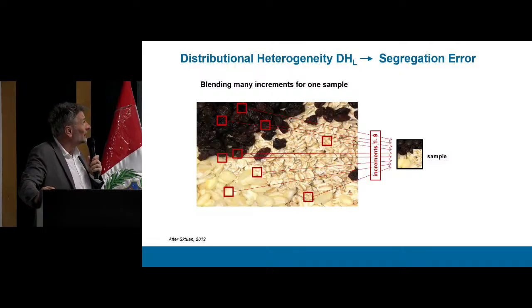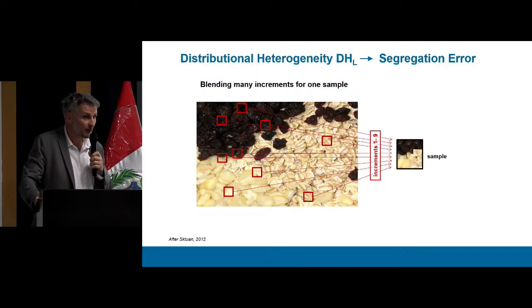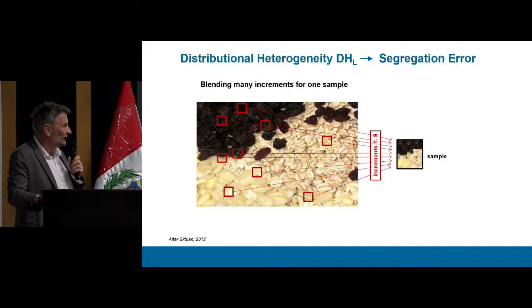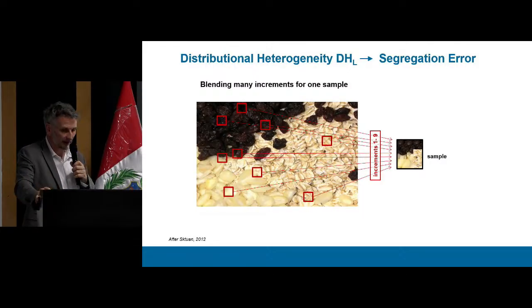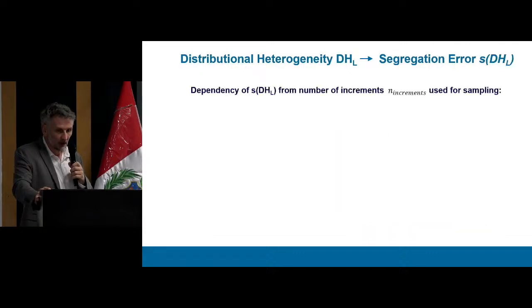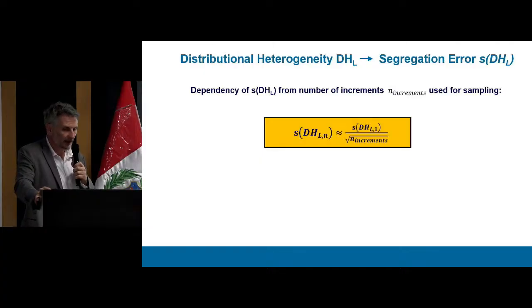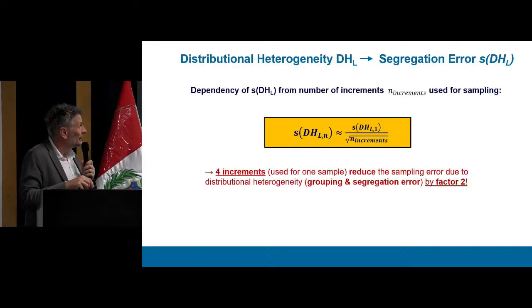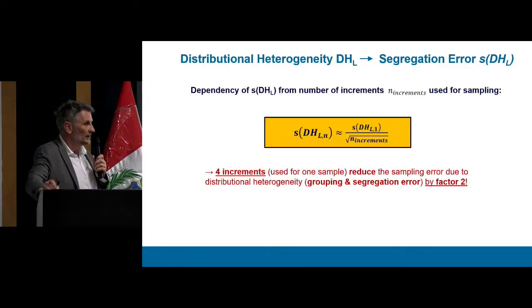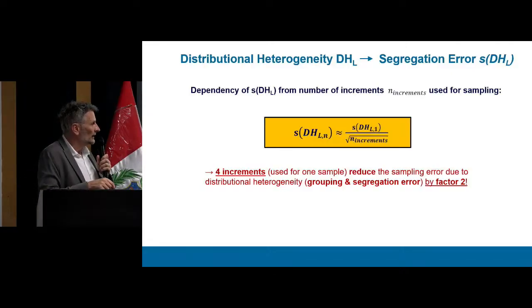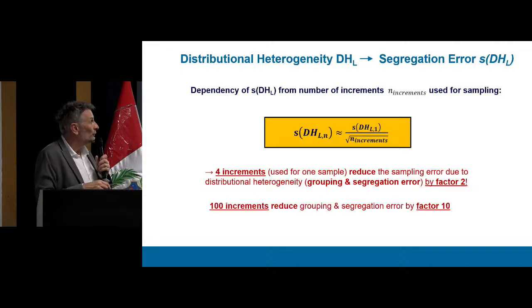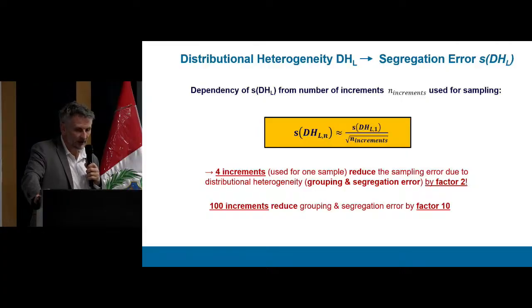So distributional heterogeneity can be covered by having a lot of increments. Another option in order to improve the sampling here would be to mix the lot, but very often this is not feasible, so we need to try to take samples from different places. The number of increments we take helps us to reduce the segregation error, and typically it reduces the segregation error by the square root of the number of increments. So when we take 4 increments from different places, we can reduce the segregation error by factor 2. If we take 100 increments, we can reduce the segregation error by factor 10.